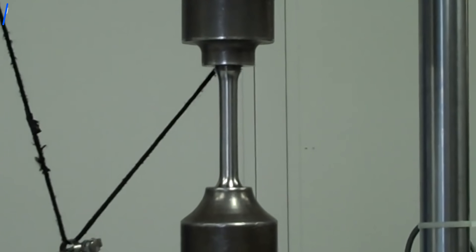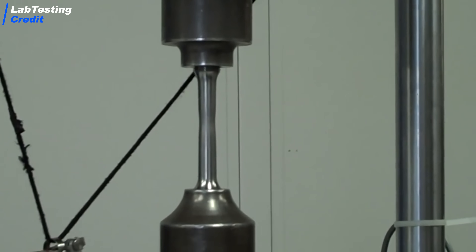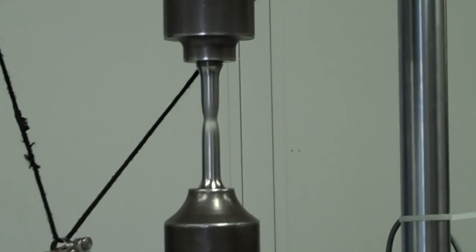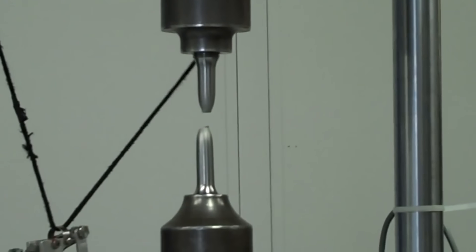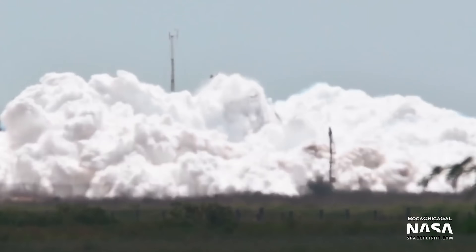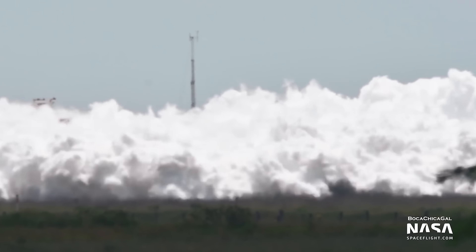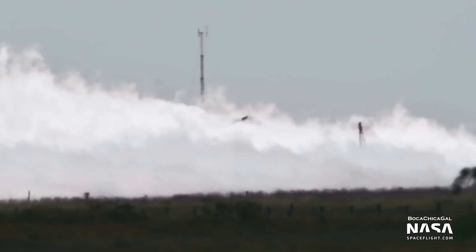A metal with higher ductility at cryogenic temperatures deforms more before it breaks — it's therefore not so brittle, which is a material characteristic we would like Starship to have. We want Starship to deform at high pressures rather than break. This new alloy is only 10–20% more expensive than 301, and the increased ductility leads to far more graceful failures at high pressures, meaning we would see leaks before bursts. Leak before burst is highly desirable because we don't want the tank to explode — we want a leak to form where the overpressure gets ejected as a benign release.